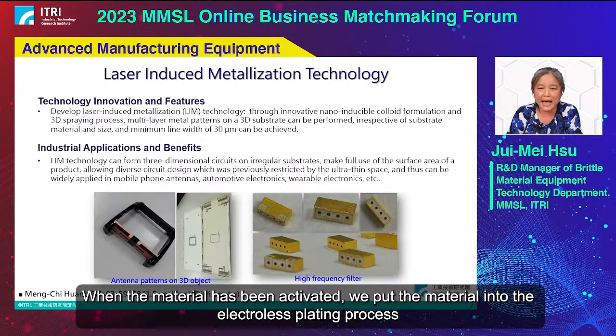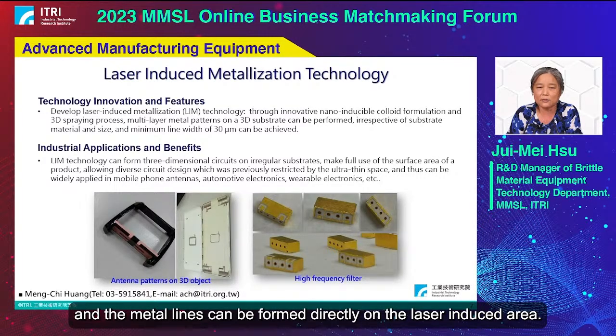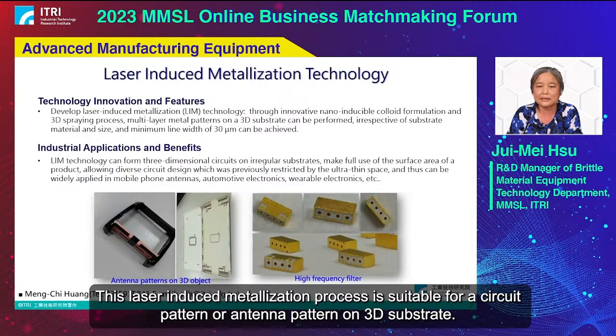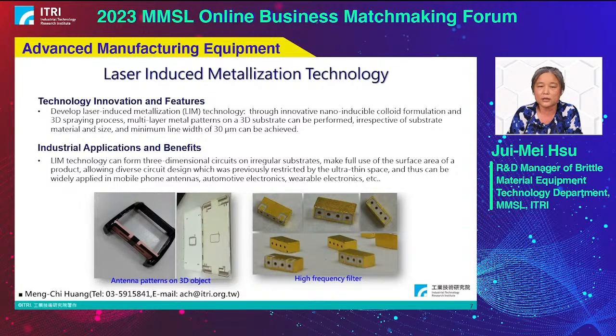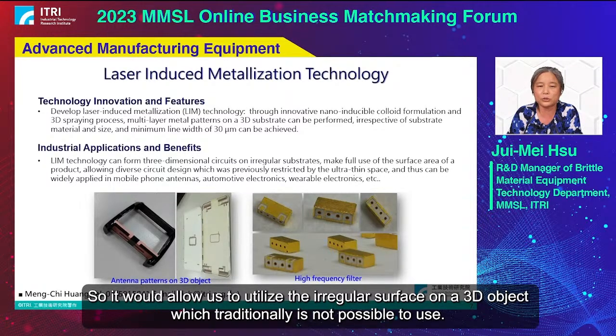When the material was activated, we put the material into the electroless plating process. And the metal line can be formed directly on the laser-induced area. This laser-induced metallization process is suitable for a circuit pattern or antenna pattern on 3D substrate. So it will allow us to utilize the irregular surface on a 3D object, which traditionally is not possible to use.